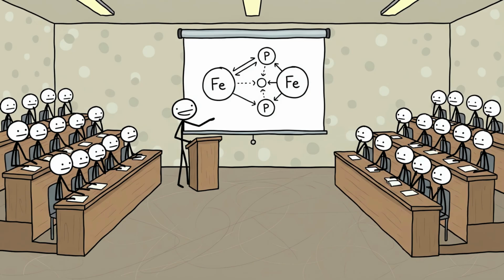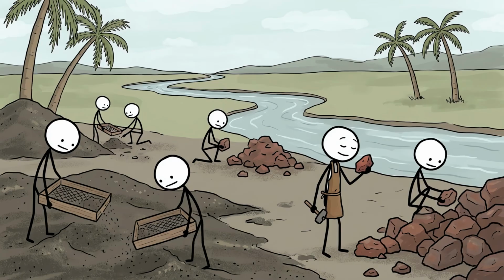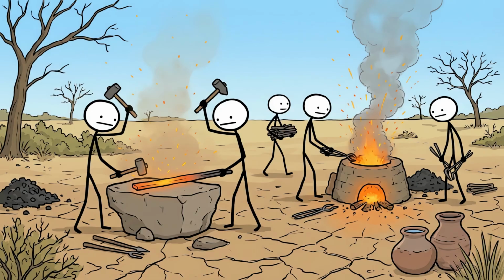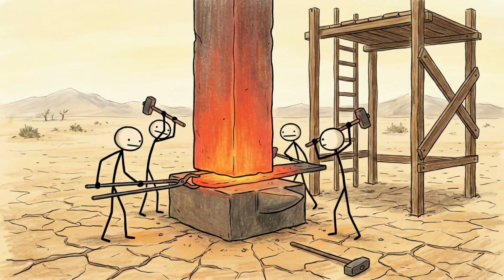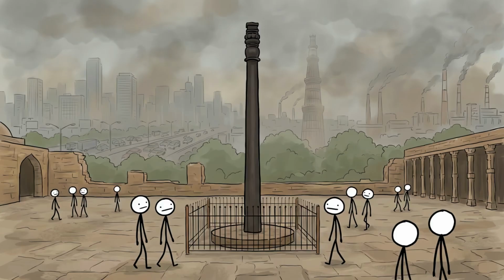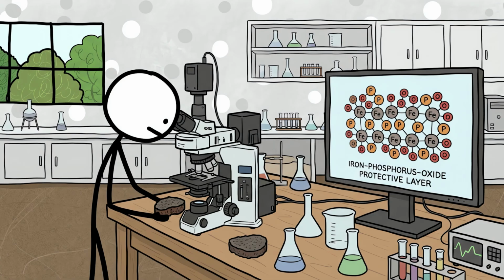The mainstream explanation focuses on chemistry and climate. Ancient Indian ironworkers empirically discovered that high phosphorus content in certain ores created a protective passive layer when forged in low sulfur, low moisture environments. The pillar's initial forging in dry conditions allowed the protective film to form perfectly. Delhi's climate, while humid, lacks the sulfur pollution of modern cities that would penetrate the layer. It's exceptional metallurgy, but explainable through chemistry we now understand.